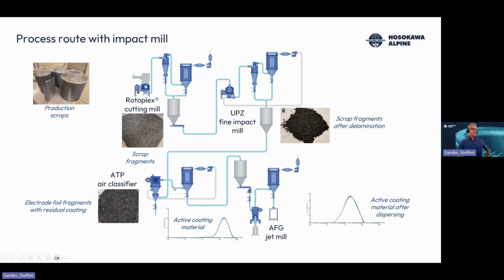So we get stressed material as a result, and here delamination of the material has taken place. In the next step, we have to separate the electrode foil that still carries some residual coating material, and the fines of this classification step, this is the active coating material. Of course, the binders, the additives are still present in this as a mixture. As you can see from the particle size distributions down here, this material is way too coarse to bring this back to the actual electrode manufacturing process. That's why if you would really like to go the direct way, you would have to process the material further. For instance, with a jet mill, fluidized bed jet mill, and you can see you can easily obtain the same particle size distributions you are used to with the virgin materials.